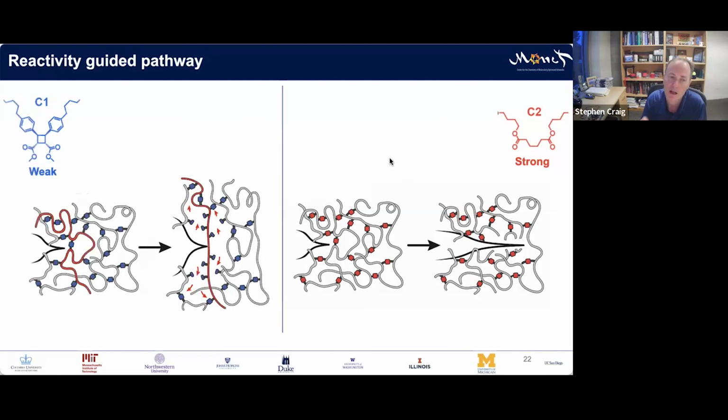On the other hand, now if I've put a mechanophore in there, I'm really a composite at the molecular level, right? I've got these long primary strands. They're strong. They're just conventional carbon-carbon bonds. But now I've cross-linked them through these very reactive, mechanically reactive cyclobutane cross-linkers. And so on an event-by-event basis, maybe the crack doesn't just go where the tension is greatest, it goes where the reactivity is greatest, where the response to that tension is the most sensitive, right?